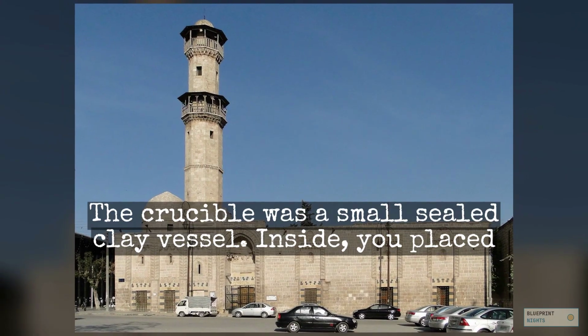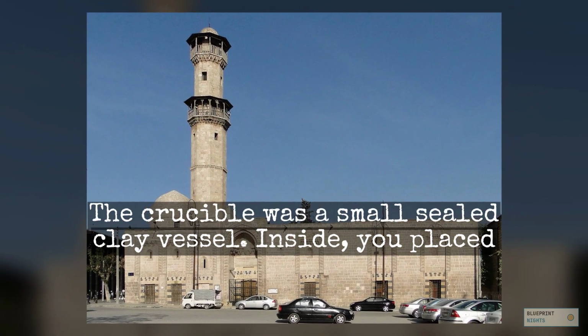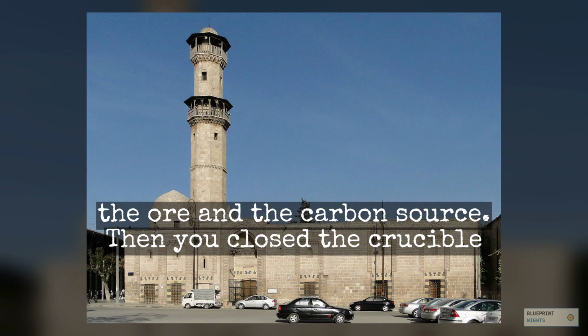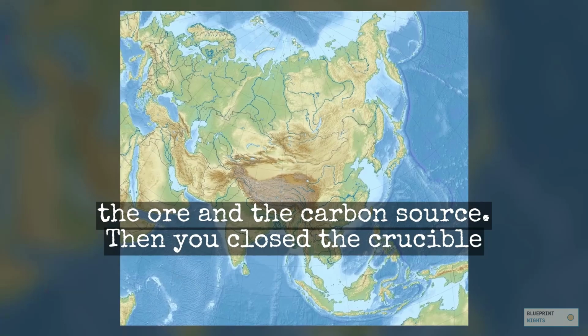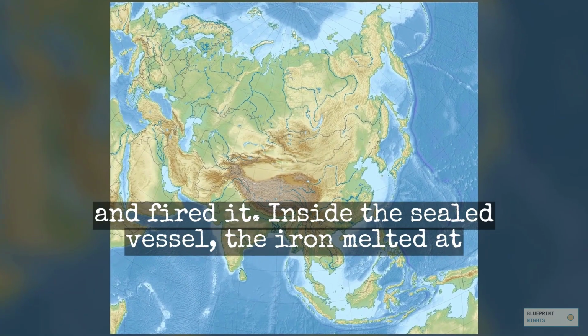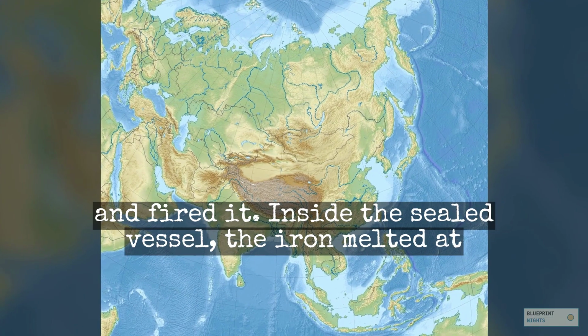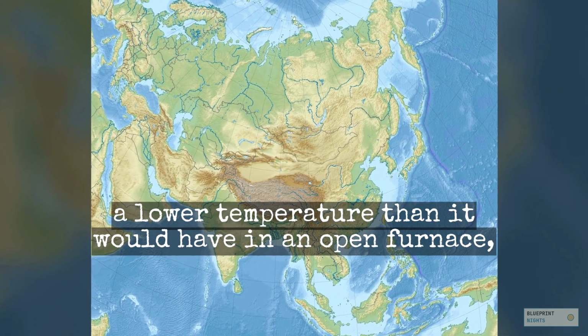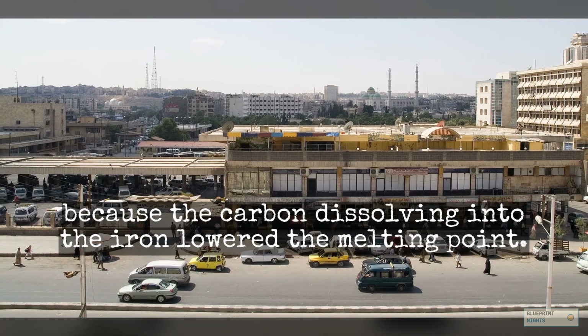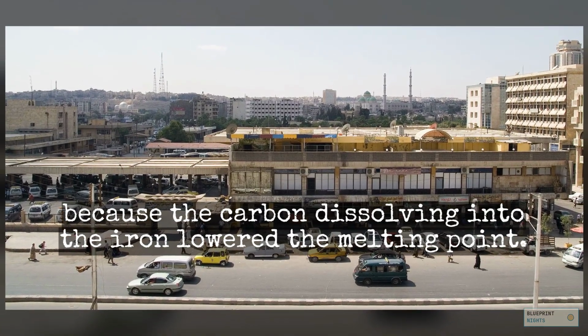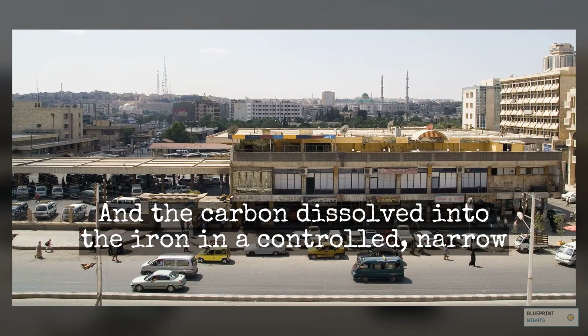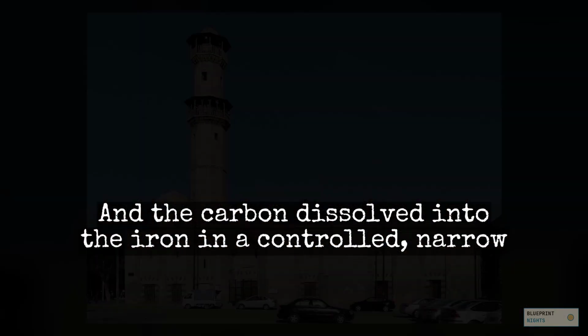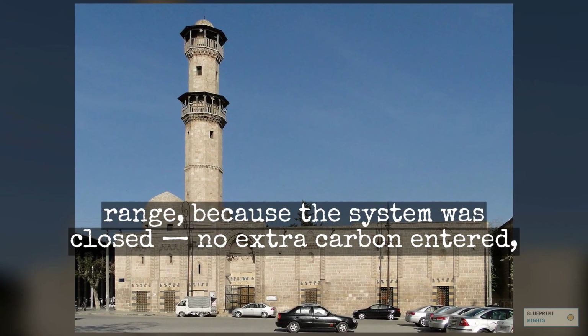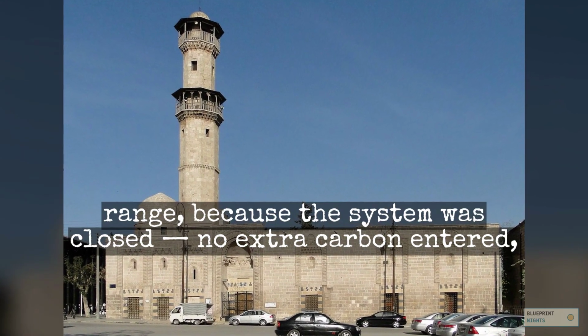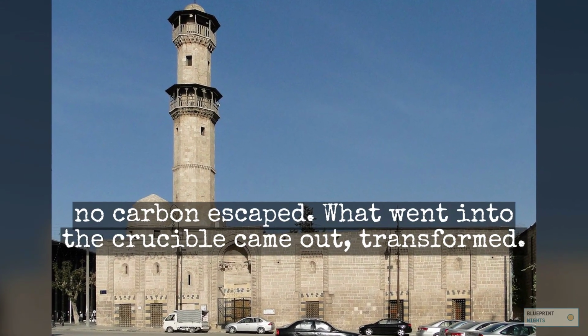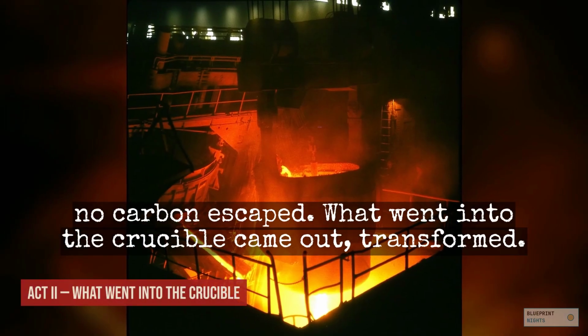The crucible was a small sealed clay vessel. Inside, you placed the ore and the carbon source. Then you closed the crucible and fired it. Inside the sealed vessel, the iron melted at a lower temperature than it would have in an open furnace, because the carbon dissolving into the iron lowered the melting point. And the carbon dissolved into the iron in a controlled, narrow range because the system was closed. No extra carbon entered, no carbon escaped. What went into the crucible came out, transformed.